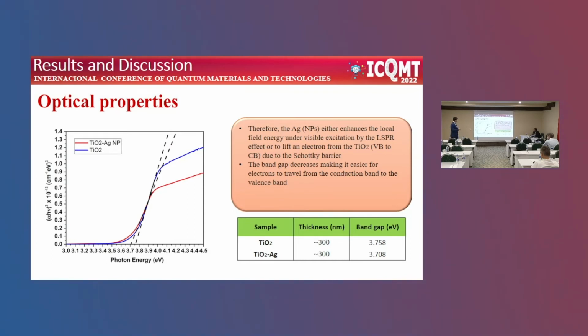Well, when we measure the optical band gap using the Tauc plot, the change of the band gap is not too high. You have 3.7 for the titanium oxide, and 3.7 for the titanium oxide coated with the silver nanoparticles. Is it normal? Yes, because you are not doping the material. You are producing a heterojunction, a Schottky barrier. You are putting the silver on the titanium oxide. You are not incorporating the silver into the titanium oxide. So if, for example, the band gap changed, probably the silver would not be on the surface of the titanium oxide. It would be inside the titanium oxide structure. So this is not the objective of this work.